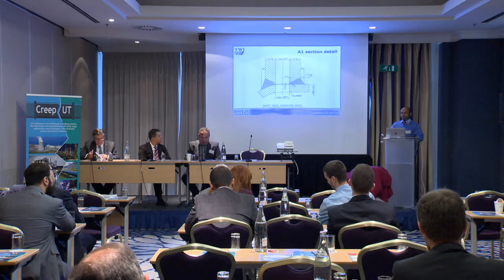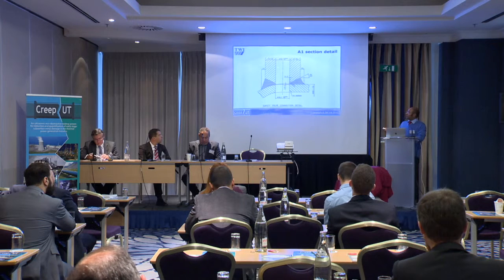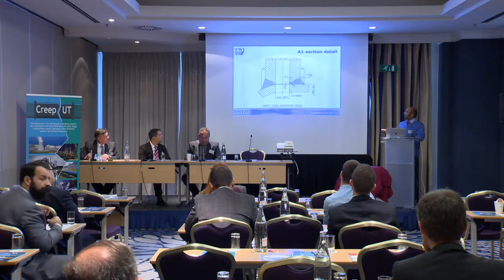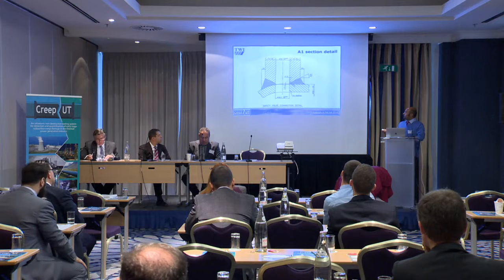So here you can see how the geometry of the weld changes around the branch, depending on whether you're at the 0 degree and 180 degree, or the 90 and the 270 degrees, as well as internal radii and changes in material conditions. This was something that we had to first of all address in order to be able to find type 4 creep damage.